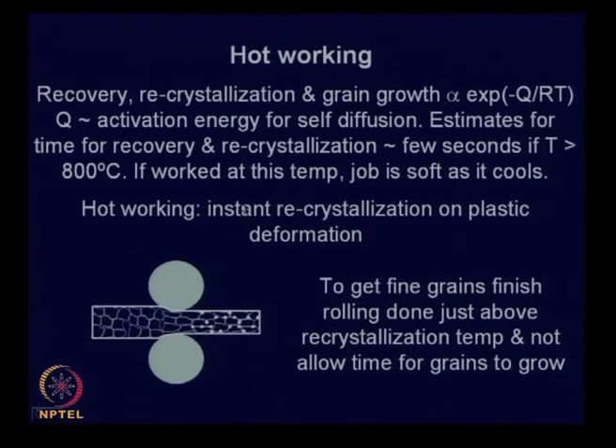Now, hot working is a process where recrystallization and plastic deformation virtually take place simultaneously. It is possible to calculate the time it takes for recrystallization to take place, because the recrystallization process will be determined by the movement of iron atoms within the lattice. So, self diffusion of iron. We know the self diffusion coefficient is given by exponential of minus Q by RT, where Q is the activation energy. So, if you know the activation energy for self diffusion, it is possible to calculate the time for recovery and recrystallization. And often, say if you do it for 800 degree centigrade, you will find that the time may be of the order of a few seconds.